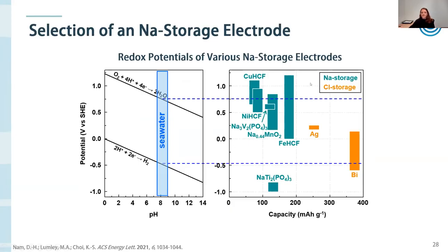And so on this graph, I'm showing the electrochemical operating windows of a few different sodium storage electrodes in blue. And you can see there's quite a few that have this HCF termination that stands for hexacyanoferrate. And these materials belong to a class of materials called Prussian blue analogs, which are probably the most widely investigated materials for sodium storage in aqueous solutions. And so we decided to look at Prussian blue analogs as well.